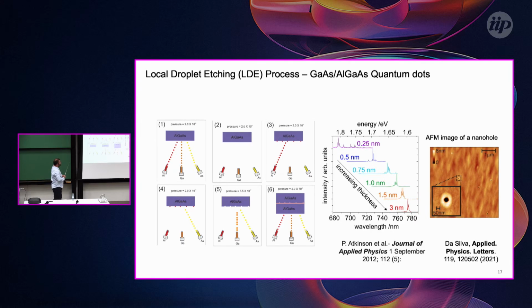And basically, here is the method. It's very related to droplet epitaxy. First, we start by growing a bottom barrier of aluminum gallium arsenide. In the second step, we close all the cells. And in this step, it's really nice when you have a cryopump, because when you want to deposit the aluminum in the next step, it's very nice if you have removed all the arsenic from the chamber, to avoid forming an aluminum arsenide layer. And in this next step, we deposit pure aluminum. This aluminum will form droplets on the surface, like in droplet epitaxy.